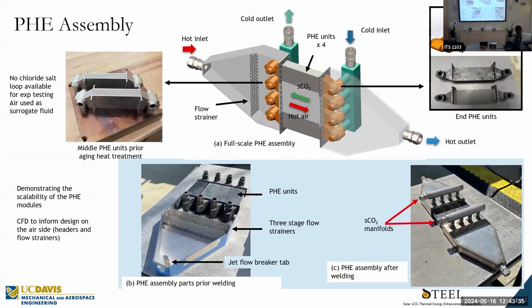So for the sake of time, I will not go over every single detail, but basically here you can see some printed prototypes. They were printed by Carnegie Mellon University. As a disclaimer on this project, all the design and experimental testing were done by UC Davis, but all the printing was done by our colleagues at Carnegie Mellon University. These units were printed out of Haynes 282, which is a nickel superalloy. And after printing, we assembled them.